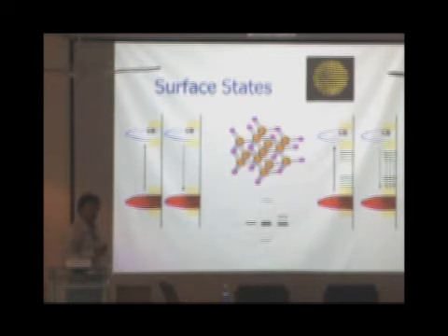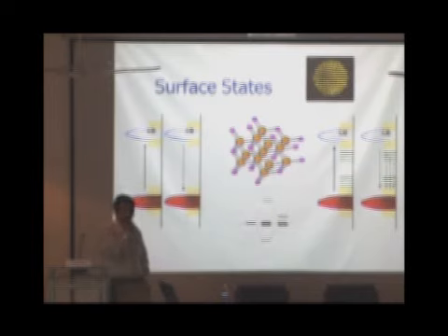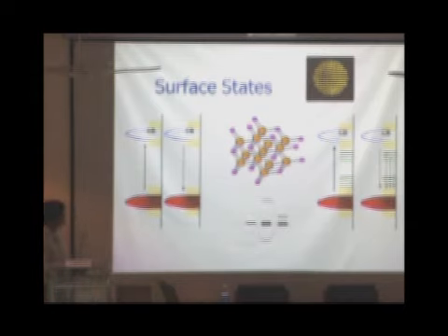Surface state emission. Now the thing is that you have a lot of surface states on nanoparticles. You can think of them, for example, as a tetrahedral bond. An atom inside in the bulk has all 4 bonds or 4 valencies satisfied, but an atom on the surface would have either 1, 2, or 3 bonds pointing outwards. So those are called dangling bonds, and dangling bonds means they are electronically placed at more or less the same level where they started with as atomic orbitals. Right? So they are not shifted anywhere because they have not bonded to anything. And if they are not shifted anywhere, they would lie between the HOMO-LUMO, or the conduction band and valence band, so within the band gap region. So these green ones are what I'm showing you as the dangling bonds.